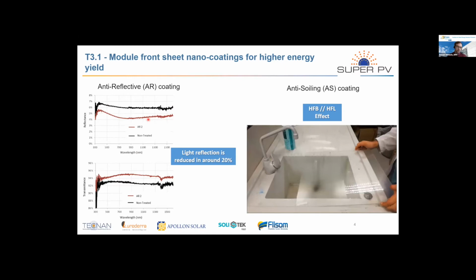And the red data shows the reflection measurement for glass coated with this anti-reflective coating based on this nanoparticle solution. And you can see that the reflection is reduced by around 20%.